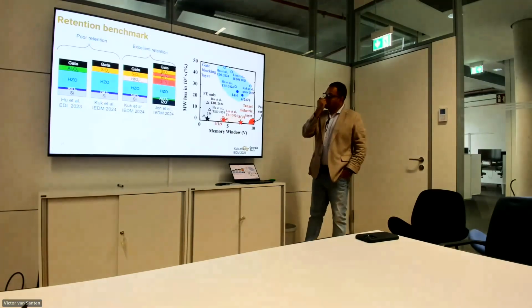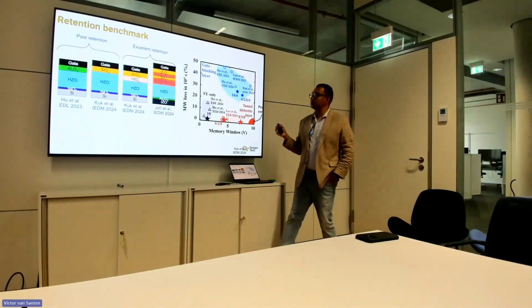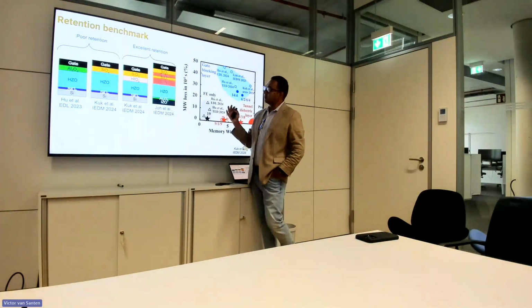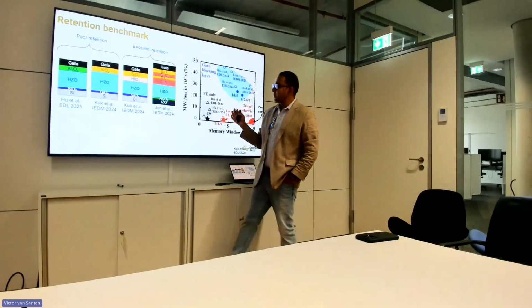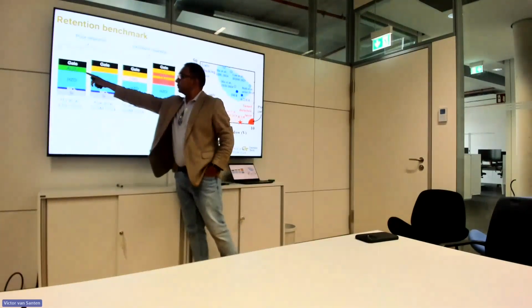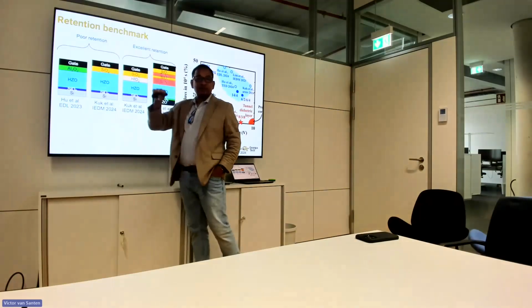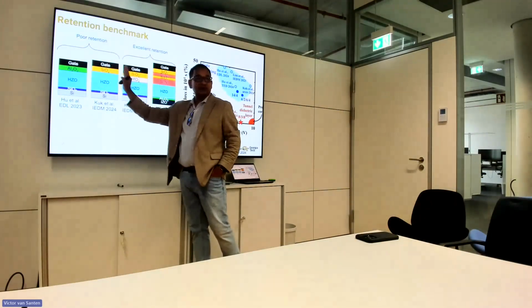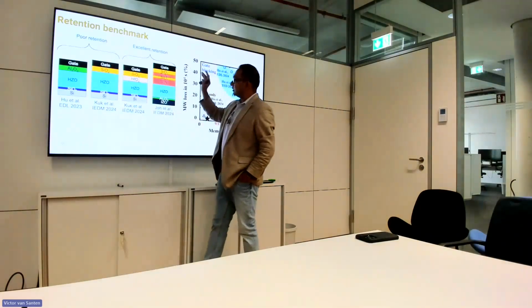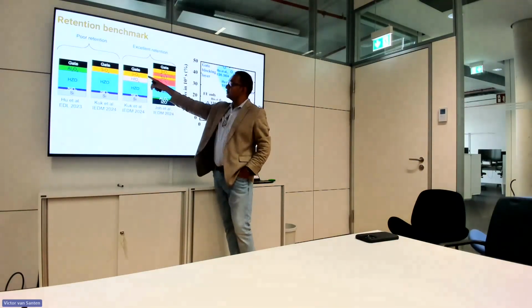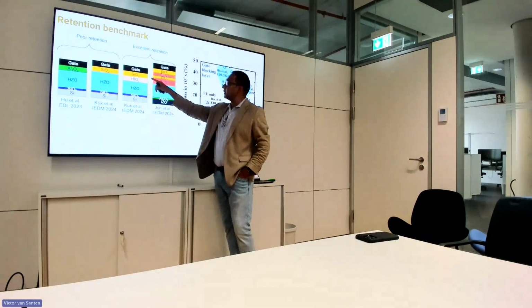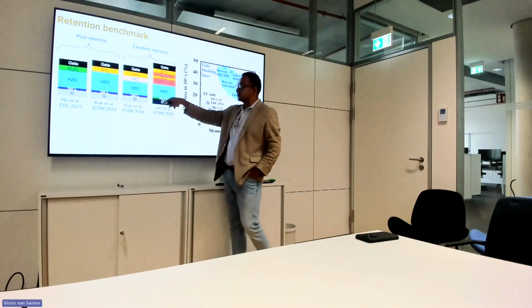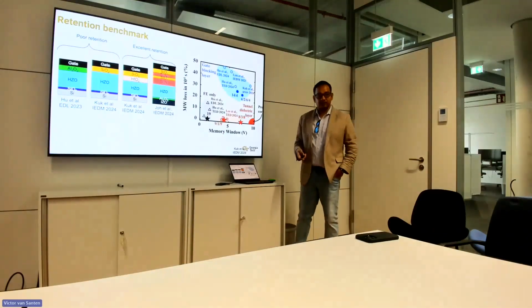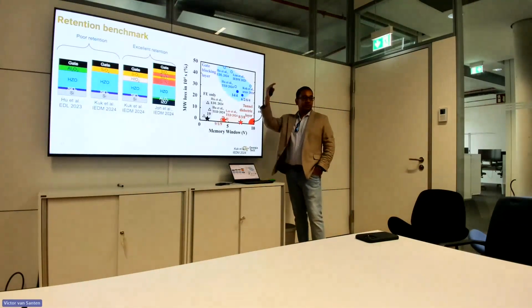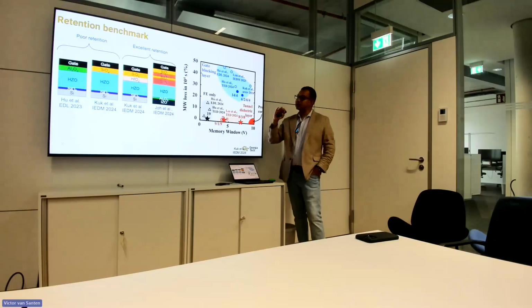Now this is not our work, it's other people's work, but just to give you a sense of all the exciting work that is happening. What people have found is that if you put a single layer on top, as in the previous slide where I showed you get very poor retention, other groups have shown that if you put two dielectric layers or multiple layers on top, then you actually get very nice retention as well. So putting a single layer on top, retention is poor, memory window is high, but if you put multiple layers on top, then memory window goes down.